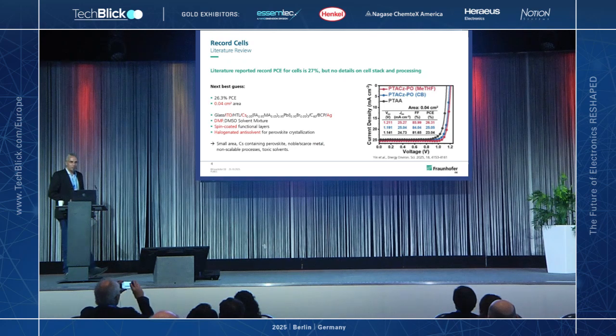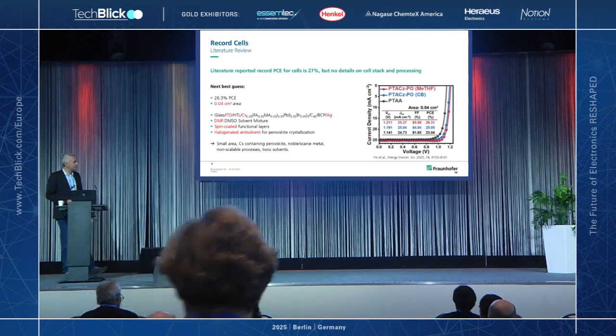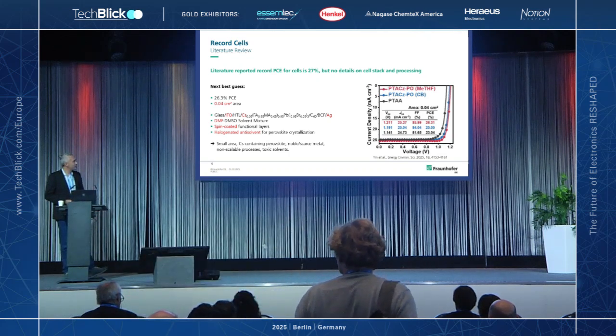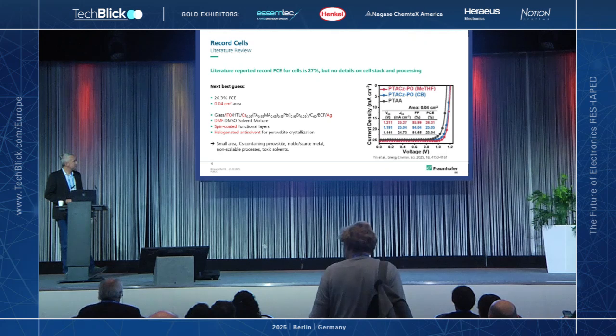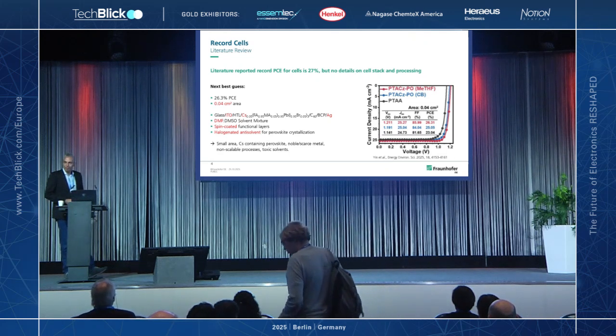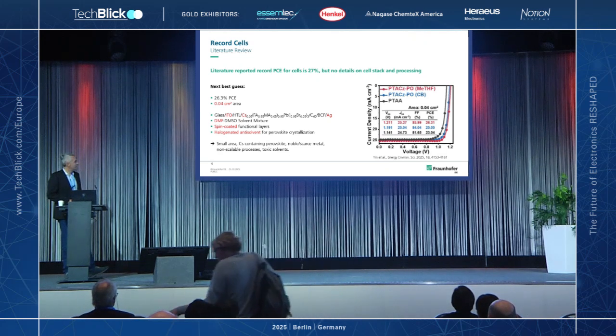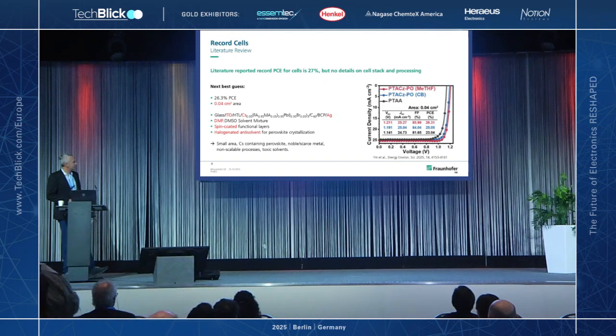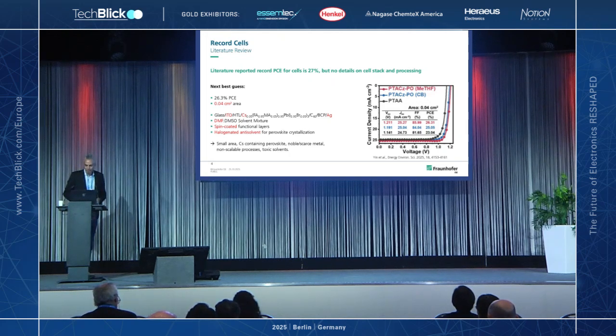And if we analyze this a bit closer, I highlighted this in red, we find some things which are a bit of a concern to me, because it's a very small area. You have cesium-containing perovskite, you have noble or scarce metals in the device stack, non-scalable processes, typically for the very high efficient devices, they are also made by spin coating, and also toxic solvents, like here the DMF, and also halogenated antisolvents, which make it even worse.